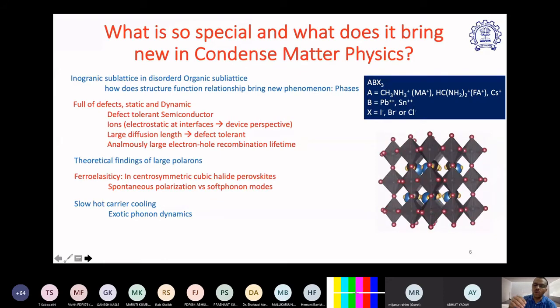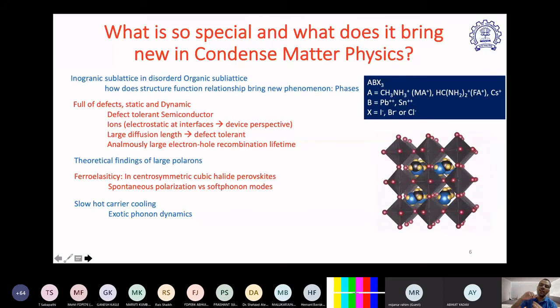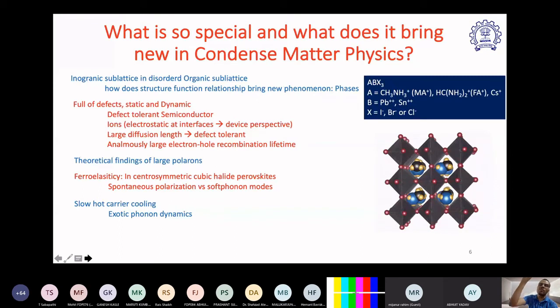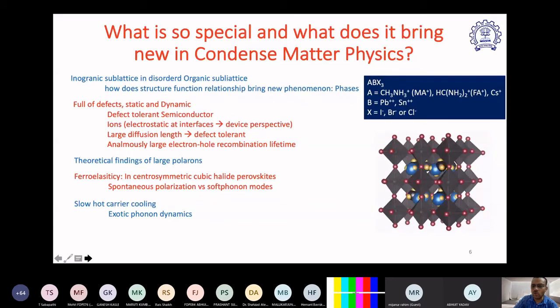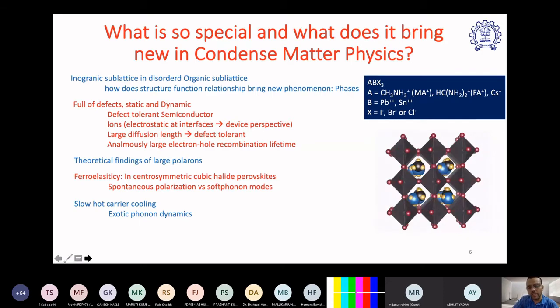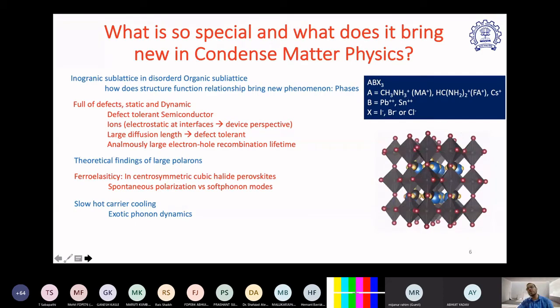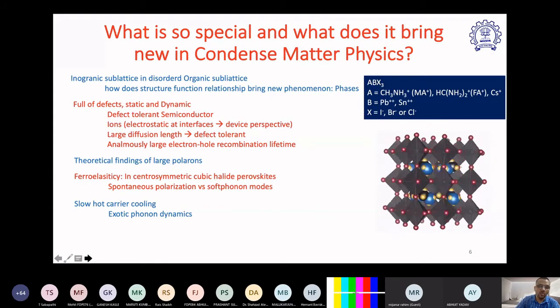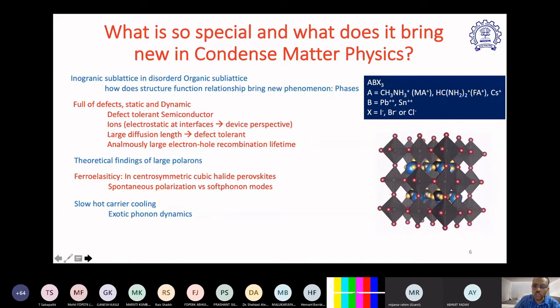At room temperature, your higher energy excited charge carrier will not be able to relax to the next downward vibration level, and that is called slow hot carrier cooling. You have a hot carrier, but it's not able to cool because the gap between the two vibration levels is much more than kBT. And this is what happens in the halide perovskite semiconductor, and they are ideal candidates for hot carrier solar cells.